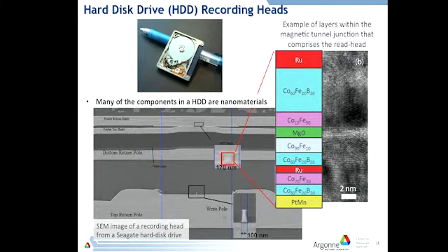It's really amazing. And if we focus in on that head, it could have all these different layers in it. There's a magnesium oxide layer here in the middle, and then these layers are cobalt iron with boron of various different compositions. There's a platinum manganese layer down here, that's an antiferromagnet. And there's ruthenium that's used as a capping layer, and also down here as a spacer.